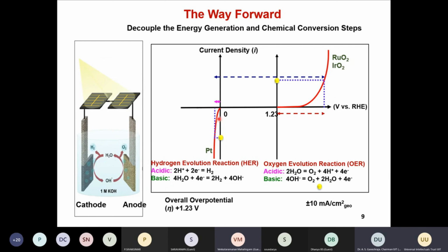So here I show the current density versus the voltage potential, and what we basically see is that ruthenium oxide and iridium oxide are benchmark catalysts for the oxygen evolution reaction. Till date, they are very good for the oxygen evolution reaction, but what you see is it always needs an extra potential over the thermodynamic potential to split water. On the other hand, the hydrogen evolution reaction is a relatively 2-electron process, whereas oxygen evolution is a 4-electron process, as I mentioned here.